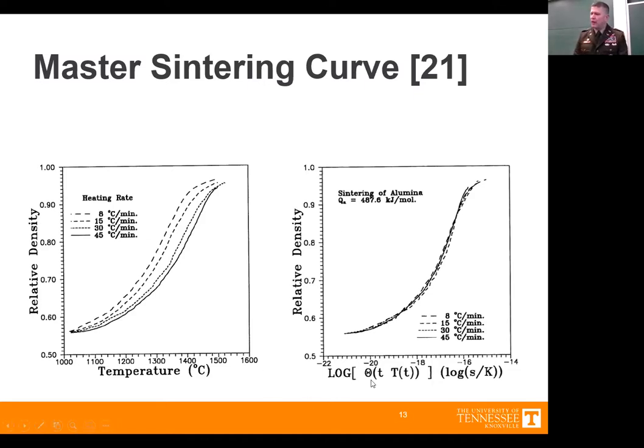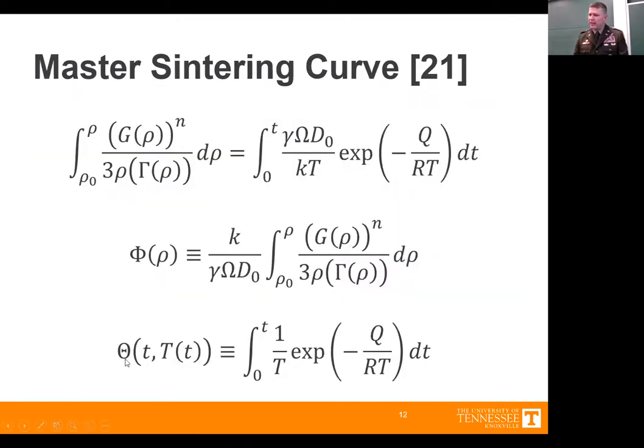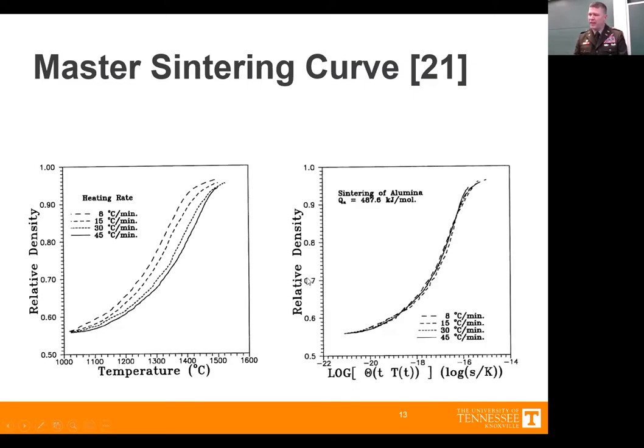By plotting the log of theta, which again is that equation, let me go back one slide, that equation right there. We take this parameter theta, solve for it, and then plot the log of theta versus the relative density, and all of those curves come together as one curve. That is the master sintering curve for this particular green body process and this particular ceramic under these sintering conditions. So no matter what heat rate you use, ostensibly anywhere between 8 degrees C per minute and 45 degrees C per minute, you can use this curve to predict how this alumina is going to sinter.